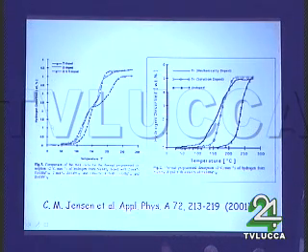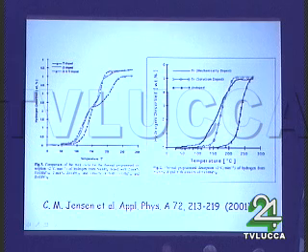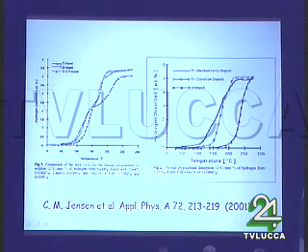So the two reactions, this is Jensen and other authors. Sorry, I wrote only the first name. The first reaction has an onset of about 50 degrees centigrade, and the second reaction 100 degrees above, when titanium catalyst is present.